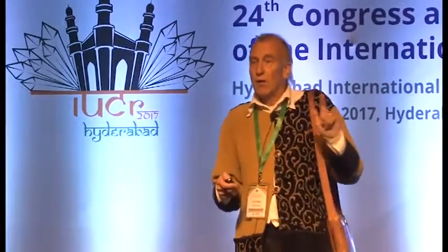This here is the first calculation of the charge distribution in such a material having mm2 point symmetry, consisting of a polar molecule, 4-iodo-4'-nitrobiphenyl, to which we will come back. With Piero Macchi, we were able to calculate these charge densities on these faces. It shows clearly that it is polar, because this is red and this is blue.